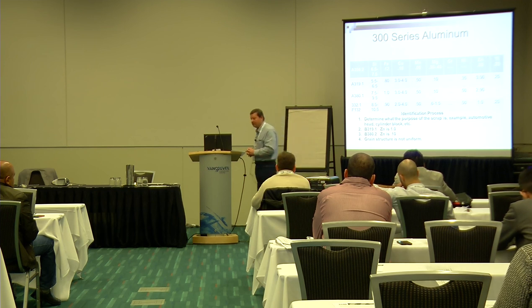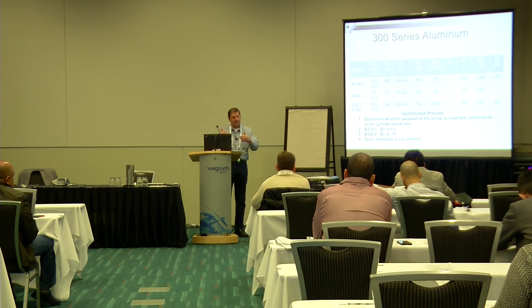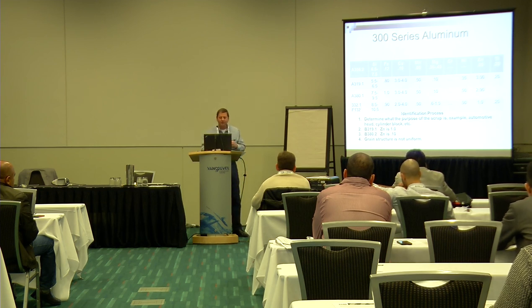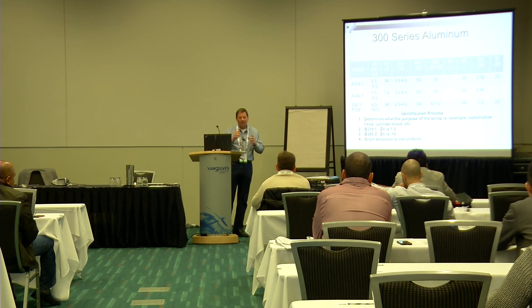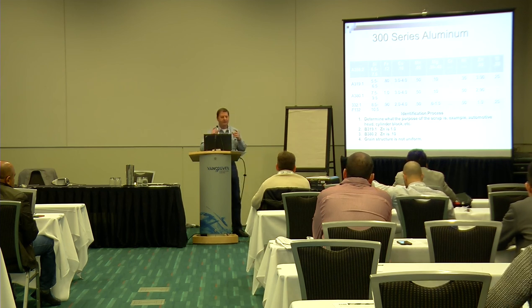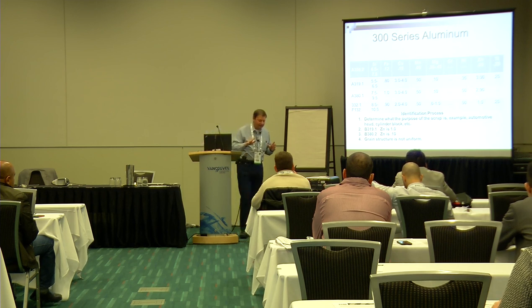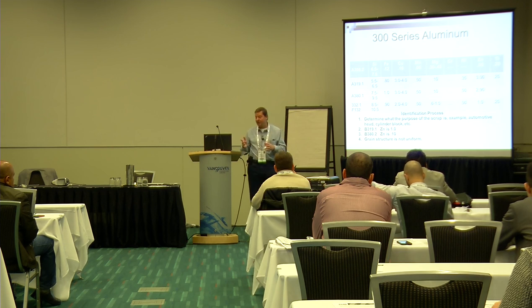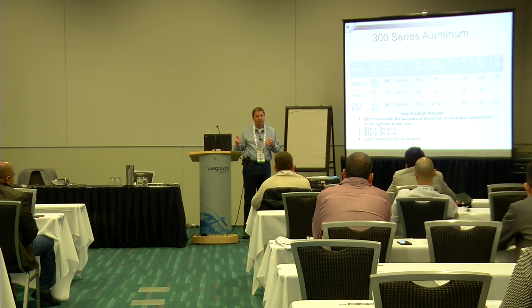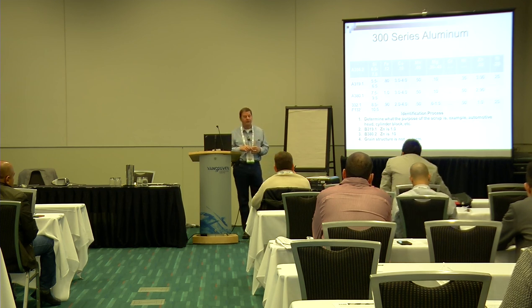And what you look at there is you see the silicon, 6.5 to 7.5. Because again, you're buying the silicon in this alloy. Because if you look at everything else, it's what we call trace elements. I mean, look at your zinc, 0.05, hardly anything. So what we basically have here is aluminum and silicon and trace elements for the rest. So if we're going to make 356 alloy, we love to put scrap wheels in. Because if we don't do that, you can make it out of prime. There's a prime, a 356 prime. But it's a lot better for us to do it this way.